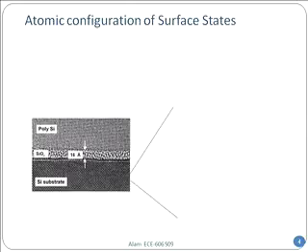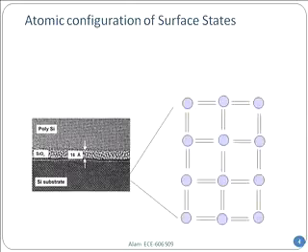So again, from another point of view, remember this particular picture: silicon on the bottom, single crystalline silicon, and then there was an amorphous oxide in the middle region. Here I show 16 angstrom. These days, most transistors have about 12 angstrom of oxide. It's even thinner than DNA. Double-stranded DNA is 22 angstrom, so this is almost half the size of the DNA, and then the polysilicon gate.